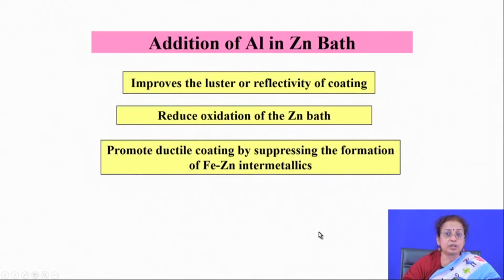If you are interested in getting rid of the intermetallics, as I mentioned, you have to add some ternary elements into the molten zinc bath. Usually aluminum is a very popular ternary element which is added in the molten zinc in order to reduce the kinetics of this intermetallic formation.